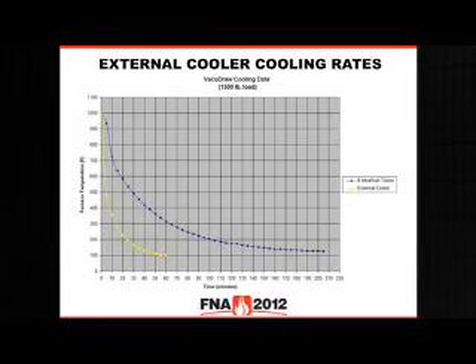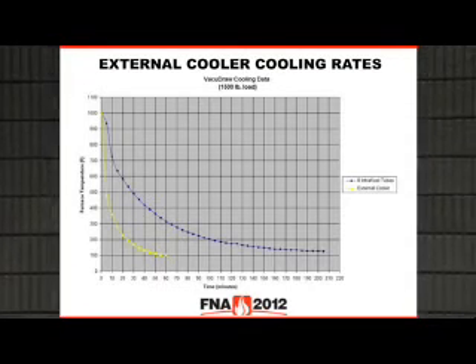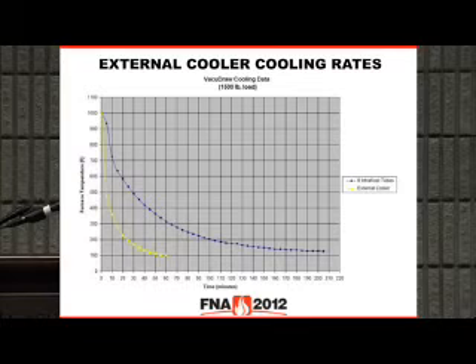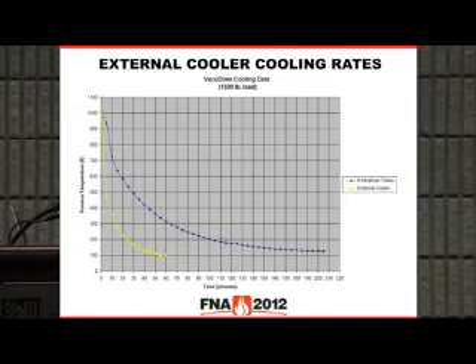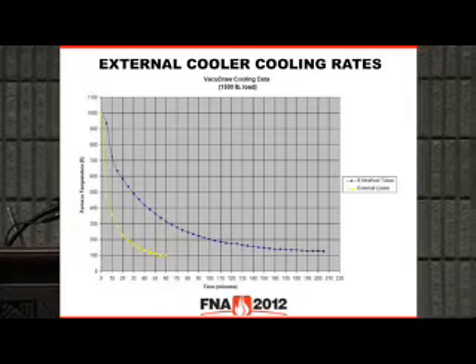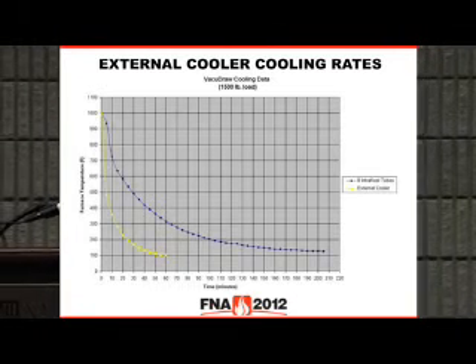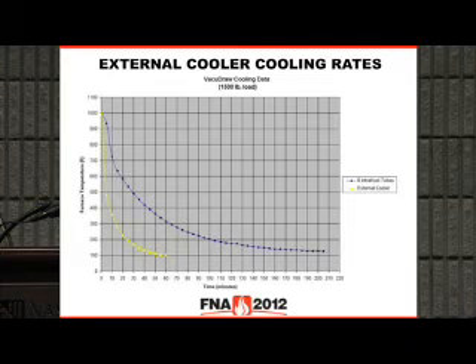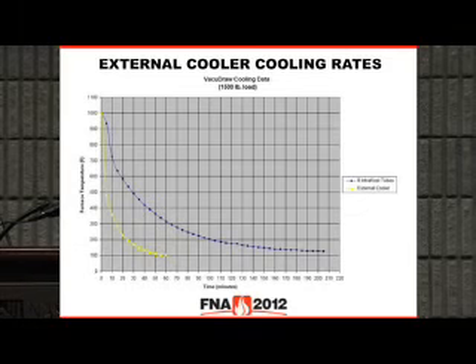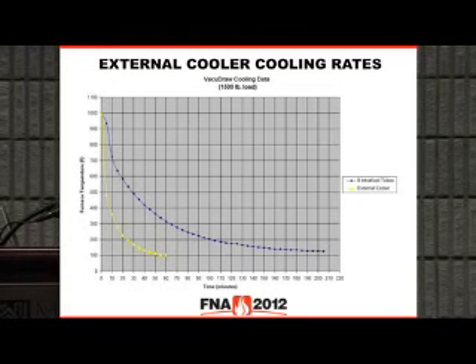This kind of just gives you a feel. This was a 1,500-pound load, and intercool would bring that down from 1,000 degrees roughly to, and I always kind of call it, about 150. If you're doing stainlesses, you'll want to get them down to 150. If you're doing carbon steels, you could actually pull out sooner, and you can pull out sooner with copper too. But for your stainlesses, they're more prone to discoloration, so you'll want to get the loads down as cool as possible. So this shows approximately getting to 150, taking somewhere about 2 hours. The external cooling system would get you down to 150 in roughly 30 or 40 minutes.